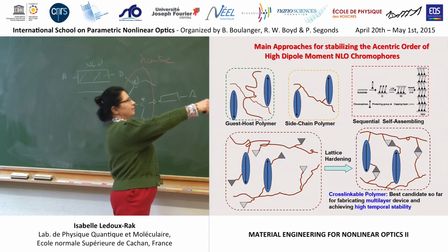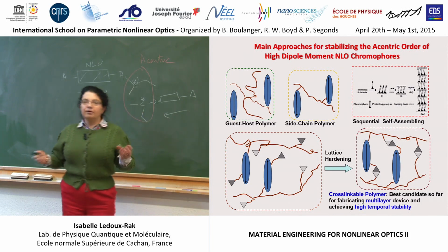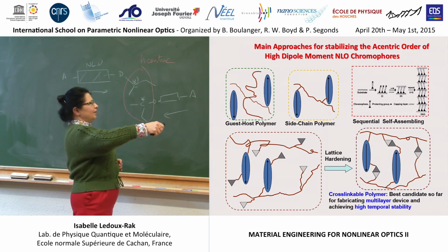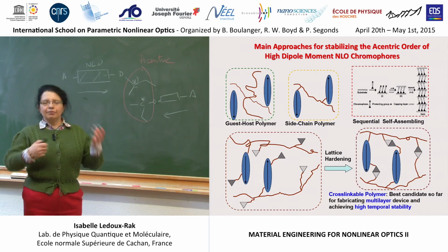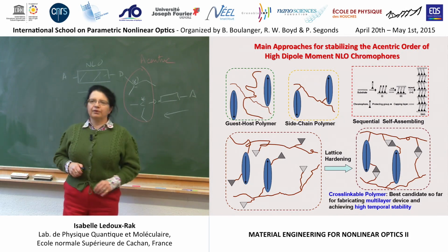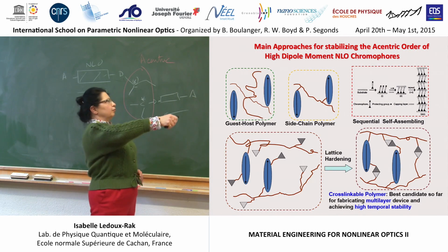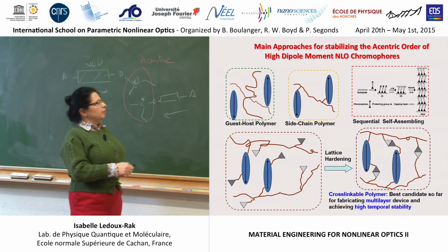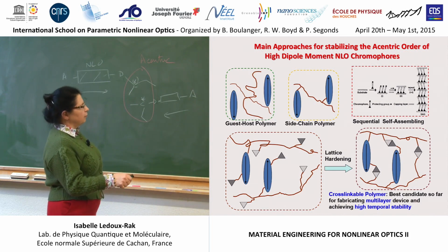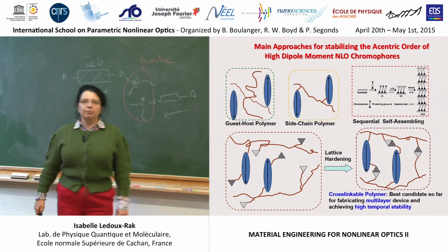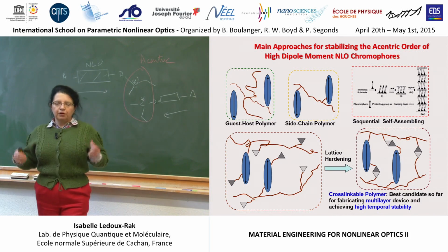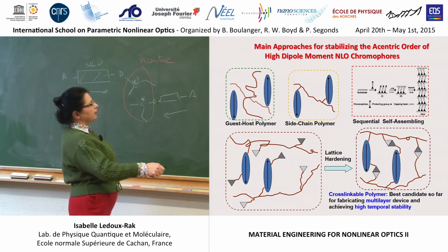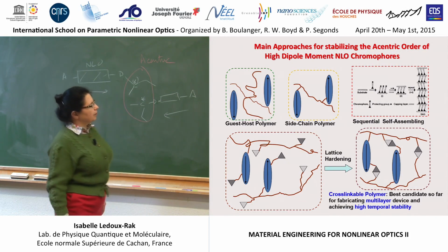They are still located in some cavities, even in solid state, and because they can feel each other, they tend to go back to centrosymmetric orientation due to possible rotation of some molecules in their cavities. So a method to improve it is to attach the molecule to the polymer chain by chemical bond. And because the polymer chain is relatively rigid, it strongly stabilizes the orientation of molecules.